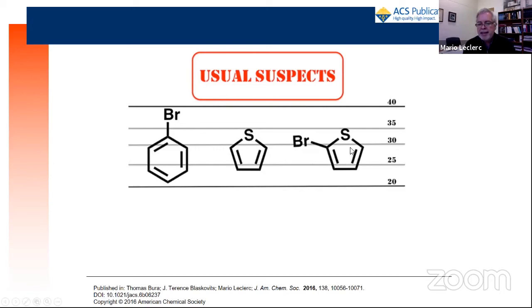If you put the bromo groups on a thiophene unit or furan or pyrrole, this kind of five-membered aromatic ring, but especially with thiophene, you slightly activate this CH bond here and make the selectivity or the reactivity not perfect, I would say less perfect. In the case of the bromo phenyl, carbazole, fluorene, isoindigo, those CH bonds adjacent to the C-Br bond are not reactive enough. So in this case, it's not reactive enough to make side reaction. This is what we believe. No proof, I repeat. But in this case, we think they are not reactive enough.